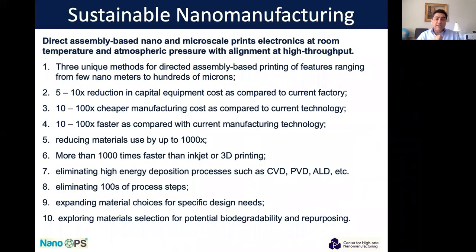For the sustainable part, this is a summary of what this technology means compared to conventional technology. This is a directed assembly based nano and microscale printing, at room temperature and room pressure, with alignment and high throughput. We can print from 10 or 20 nanometers to hundreds of microns. The capital equipment cost is at least 10x lower compared to current factories. You also have about 10 to 100x cheaper manufacturing cost compared to conventional technology. It's about 10 to 100 times faster than current manufacturing technology. I'm not comparing it with printing now, I'm comparing it with traditional semiconductor manufacturing. The material use is reduced by about 1,000x. It's more than 1,000 times faster than inkjet or 3D printing.